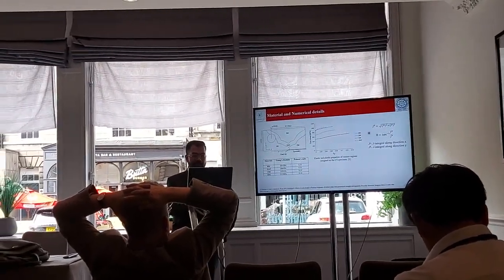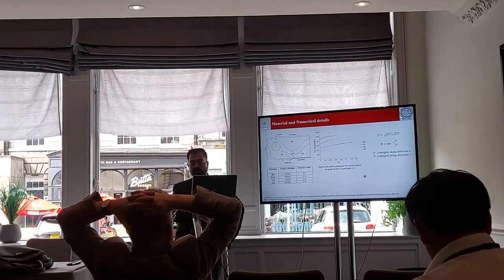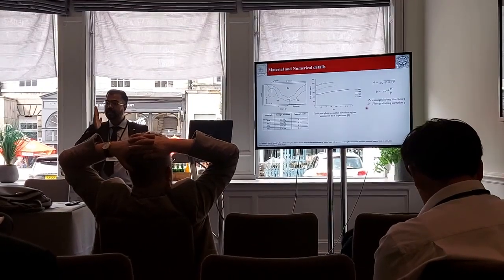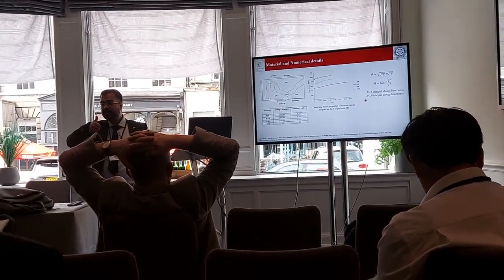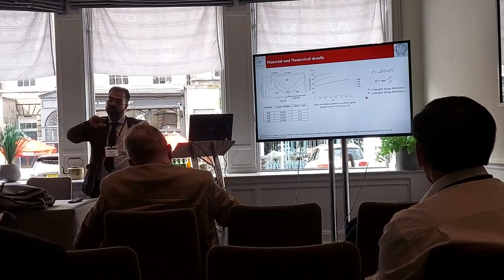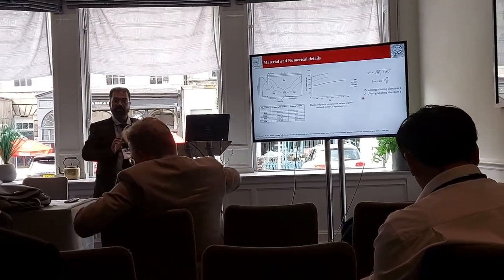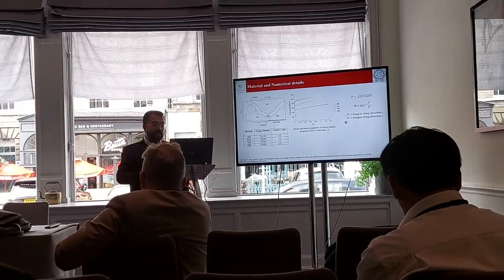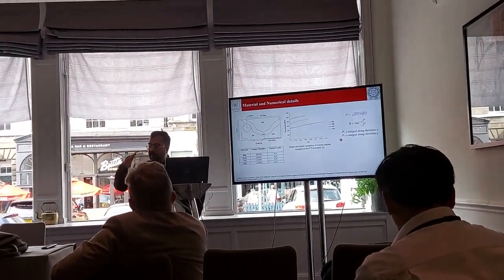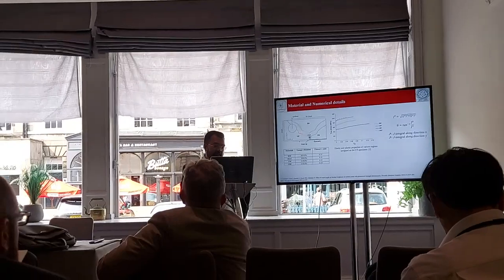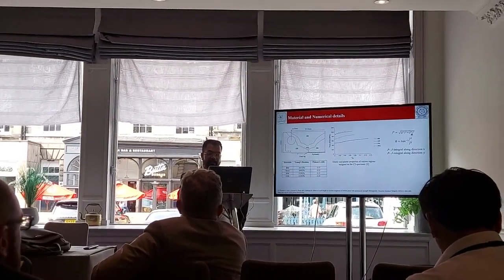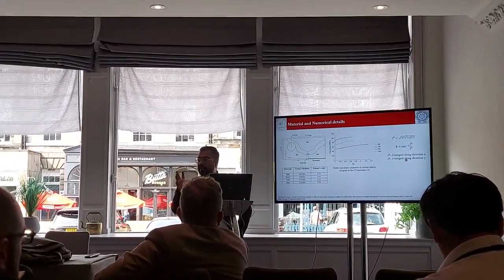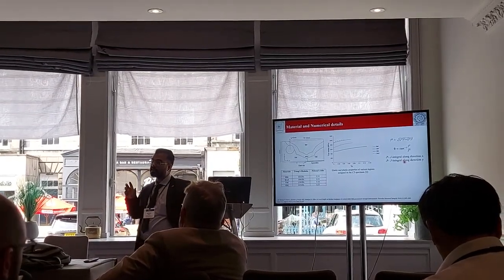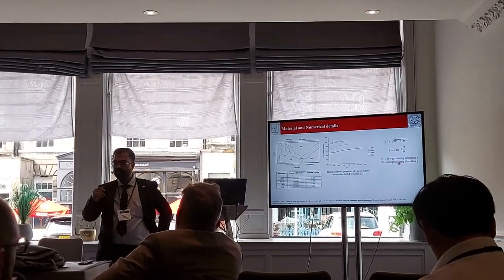So we took that geometry and we took the property of base metal, overmatching, undermatching and all those. And in this case, because the interface is not perpendicular, what happens when the interface is perpendicular? The y component of the J vector is cancelled out because of symmetry. So only Jx is taking care of the effect which is coming because of the interface. But in this case, because it has an orientation, the interfaces are not perpendicular. So in that case, we have to take the vector and find out how much deflection it can cause in the crack because of the interface.